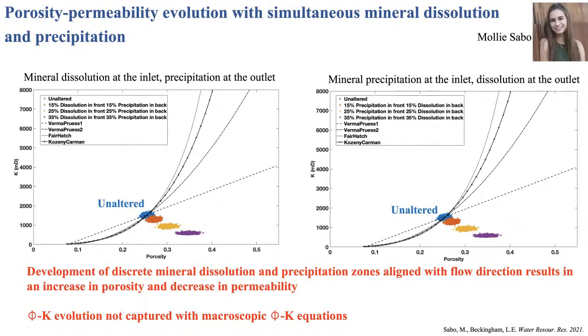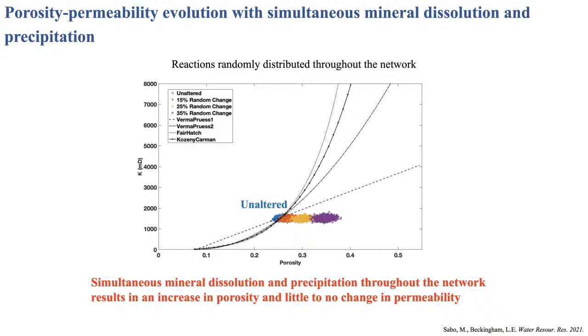And then just as a kind of numerical experiment, we consider the opposite scenario where you have precipitation at the inlet and dissolution at the outlet, and you see the same evolution of porosity and permeability. And so when you have these discrete reaction zones within your network, this is going to result in porosity increasing and permeability decreasing as the fluid has to pass through some region where all of the pore throats have been constricted, which has reduced permeability. On the other hand, if reactions are randomly distributed throughout the network, so in some places the pores and pore throats are getting bigger, dissolving, and in other places they're getting smaller as precipitation happens, then you increase porosity, but you can maintain preferential flow paths and maintain the permeability of the system.